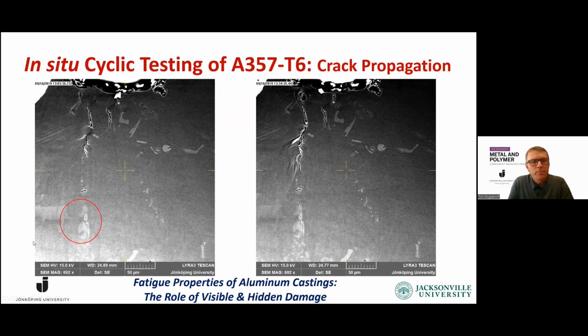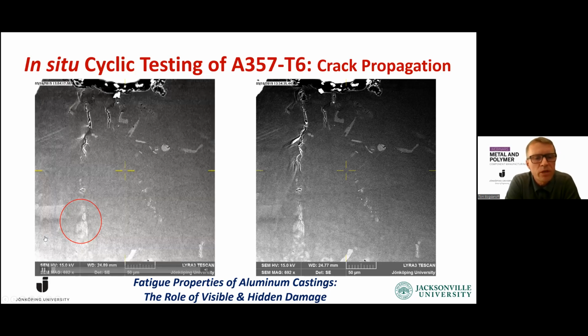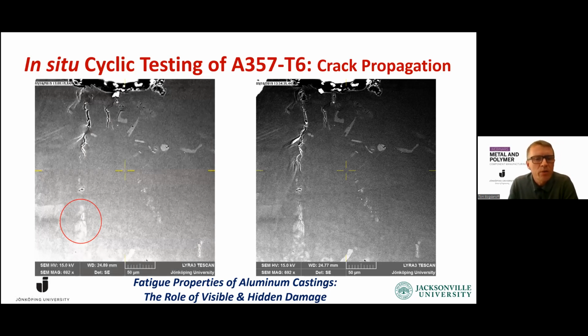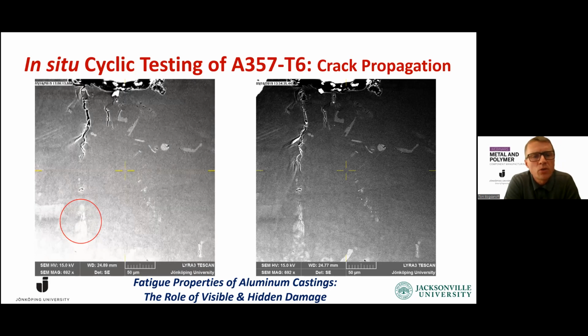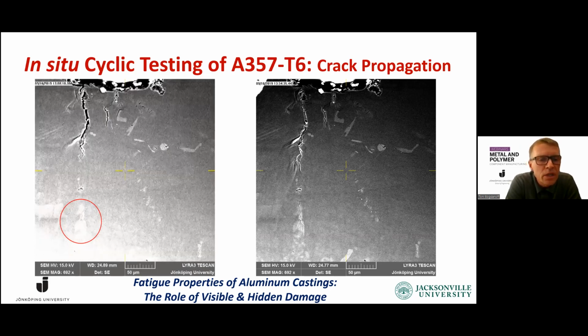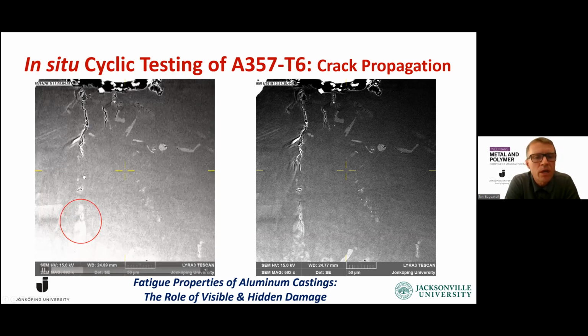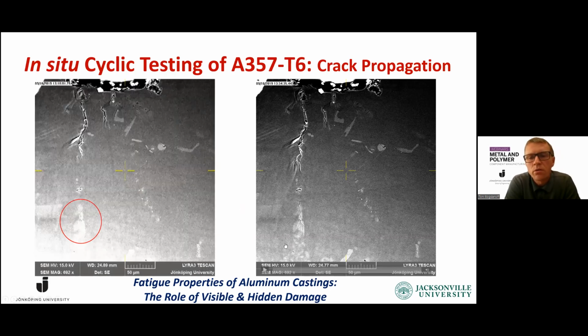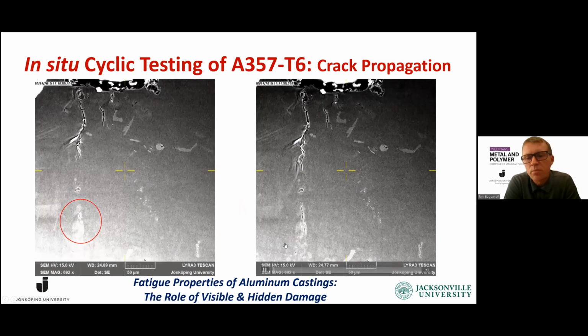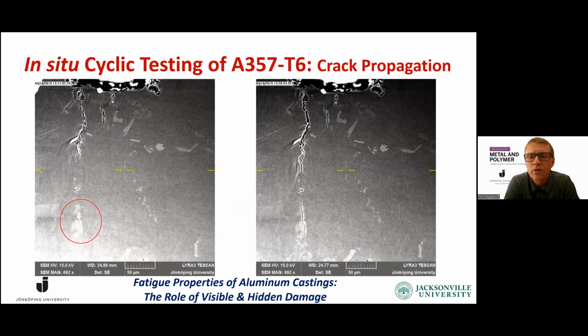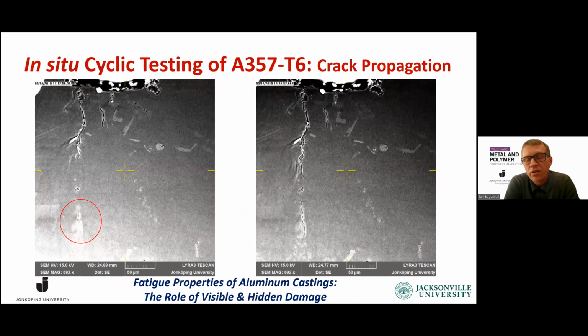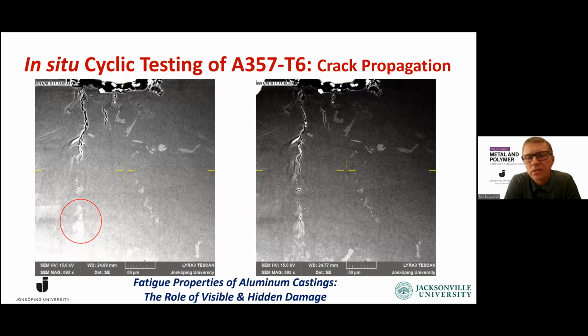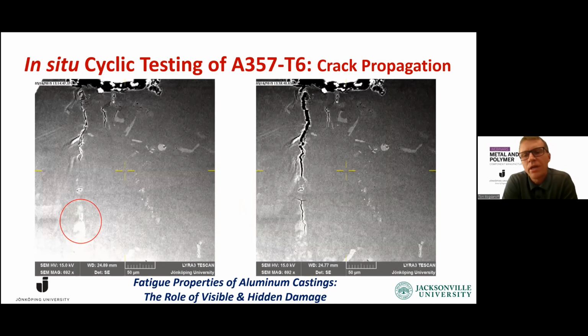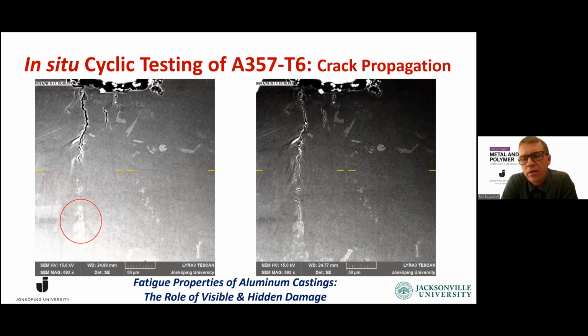This is another example of an A357 alloy that we did on the same. And what we see before we start the video is that we have cracks far down in the red ring. We still have the notch that we can follow the propagation. And we see that we have an area in between that is not at all cracked, but we still see that the crack below is growing more and more, and then the crack is propagating in the ductile aluminium area that withstands the propagation until it finally linked together with the oxide crack in front